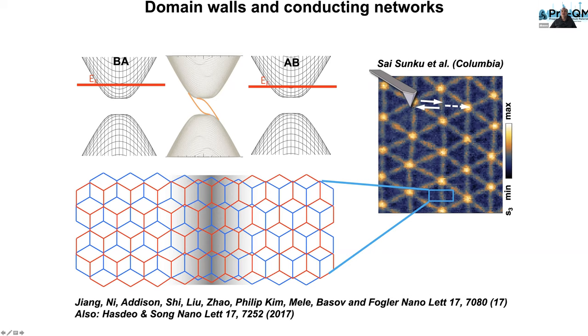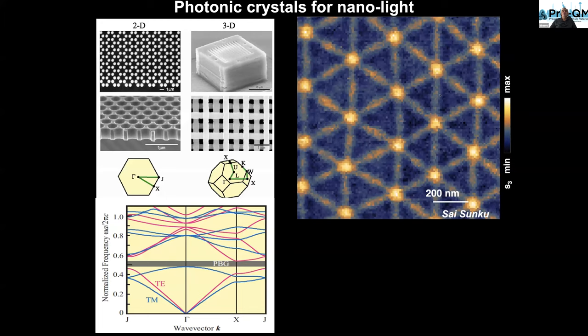So there are extra edge states that are formed at the domain wall. These are cousins of edge states in, say, quantum Hall systems, except now these edge states are present in the interior of our samples, not just at the physical boundary of our sample. And these extra states are responsible for additional conductivity at infrared frequencies that acts as a polaritonic reflector. So this periodic network of domain walls is not any different from a photonic crystal, but now for these waves. But there are some differences with conventional photonic crystals or metamaterials.